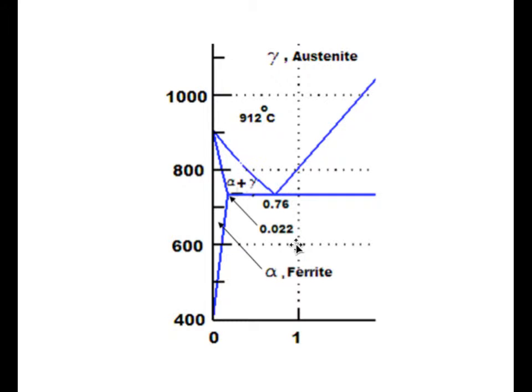And at high temperatures, what's going to happen is that we get large areas with low carbon content, and then we get larger particles. So if we wait for a long time, we get larger particles, and the whole matrix is going to be soft ferrite. And if you go really long time, we get something that is called spheroidite. It means that we start getting relatively large and round particles of cementite and a very soft matrix. Then we have got a really soft material.